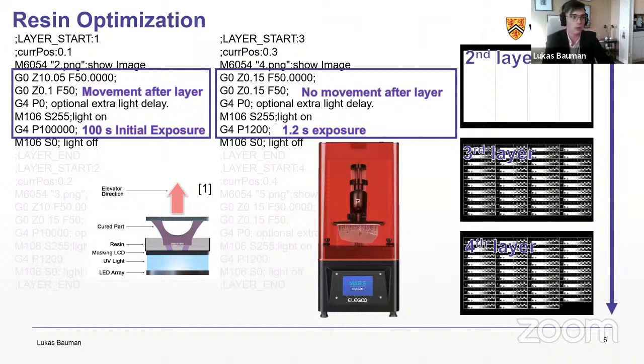So the first scale would be 1.2 seconds, and then the second is 2.4, 3.6, so on, all the way to 48 seconds. And this allows us to test a wide variety of exposure times without having to do multiple tests taking days and using quite a bit of resin.